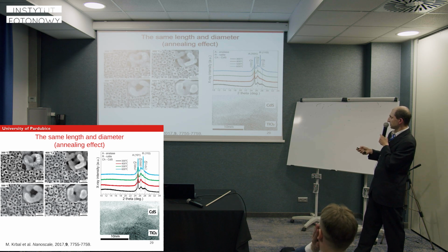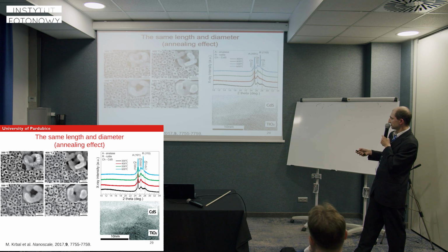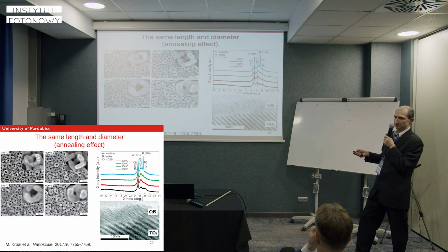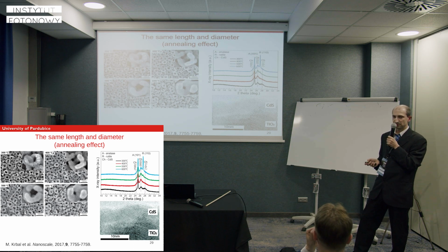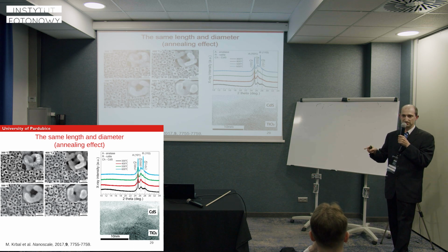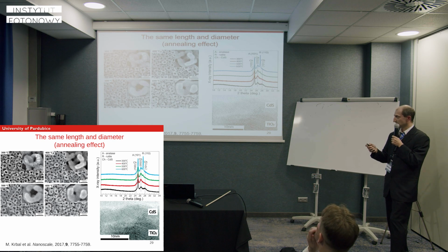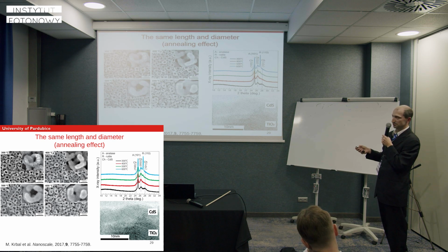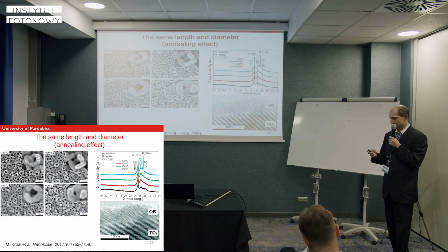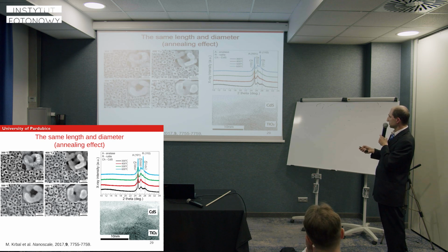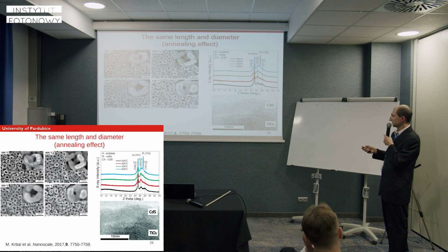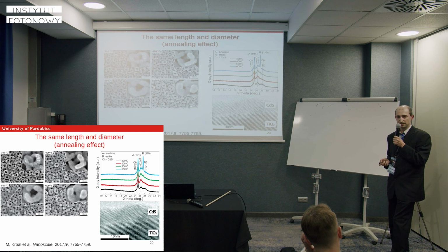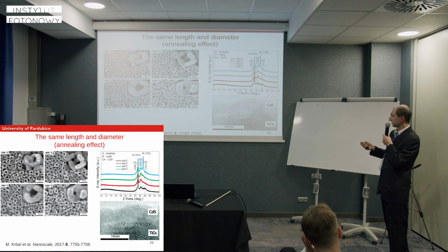If you look at the XRD, you can see that you still have some amorphous background. So the sample preheated to 300 degrees has anatase, but also still some amorphous phase. On the sample preheated to 400 degrees there is a little bit as well, but after that it's completely crystalline. We also found that the cadmium sulfide here is a hexagonal phase.